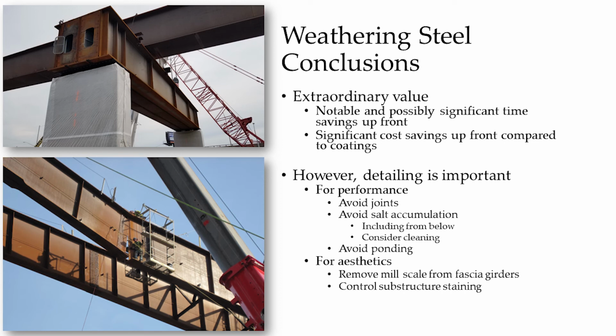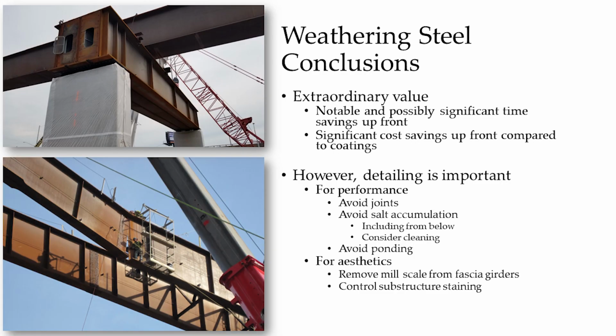You want to make sure there's no leaking on the bridge. If you're over high traffic with salt, be careful. From what I've seen, if I was in an area like urban DC, it had that tunnel-like condition, I certainly wouldn't use it. But there's plenty of other crossings that do make sense. And from the aesthetic standpoints, do be sure to remove the mill scale and control substructure staining. You use those pans I showed you, drip bars.